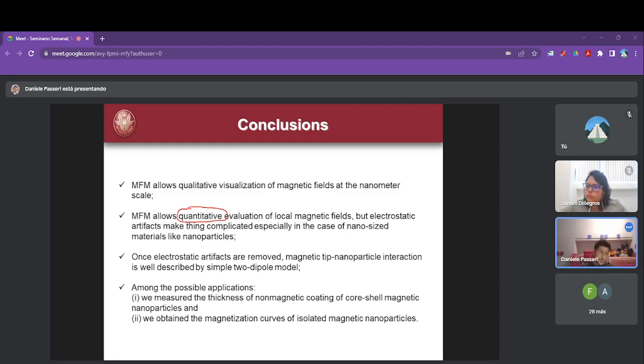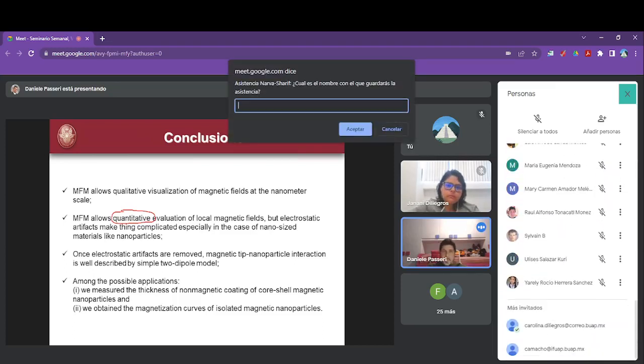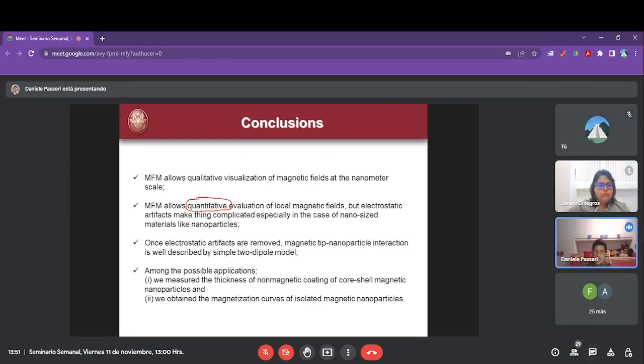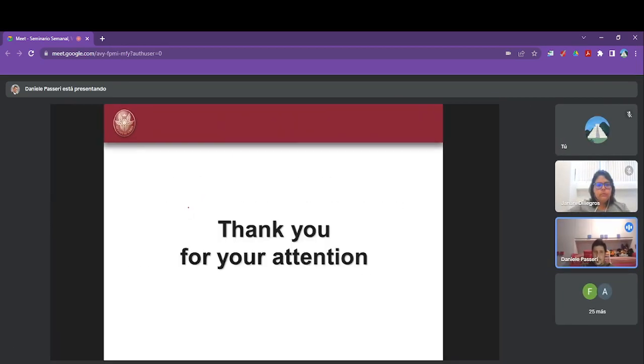I reported two of our applications: the thickness of the non-magnetic coating of core-shell nanoparticles and the magnetization curves of isolated single nanoparticles. So we selected that nanoparticle in the image and we obtained its magnetization curve. So now the last thing which is left is to thank you for your kind attention.